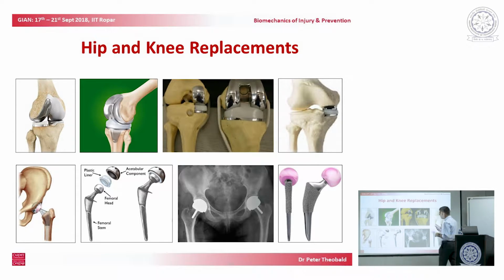So metal on metal, from a tribological point of view, seemed to be a success. You had your big head to give you the fastest possible velocity on the outside, which meant that you were more likely to reach these more preferential regimes of lubrication. The downside that the joint simulators couldn't tell you is that the wear particles that were produced were held in the synovium and that they were actually very harmful and dangerous to the body.